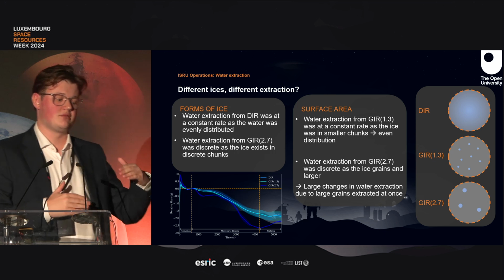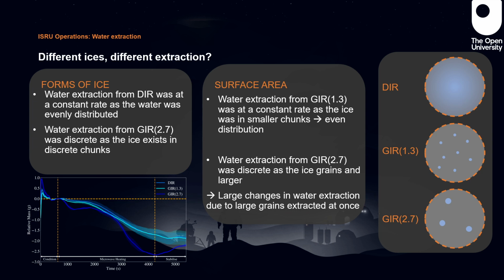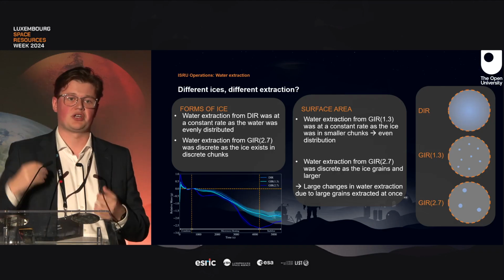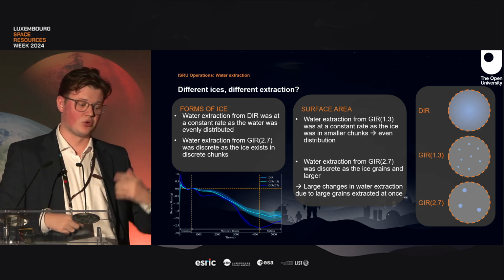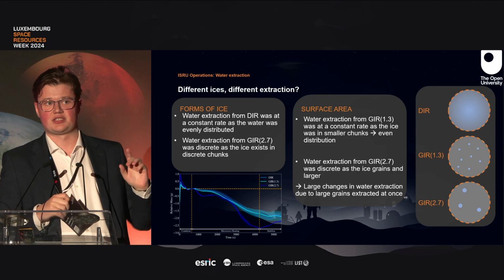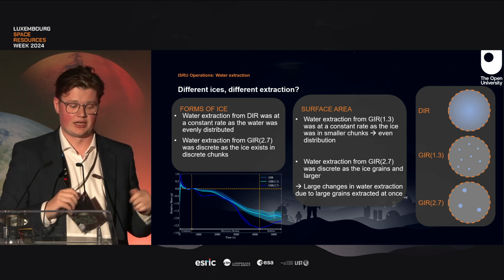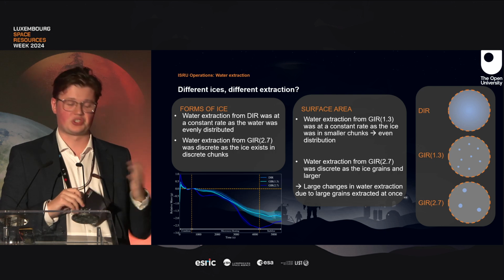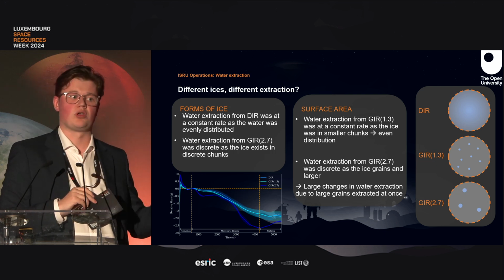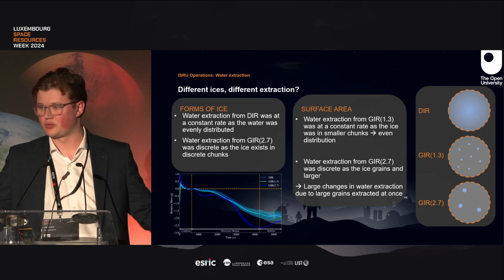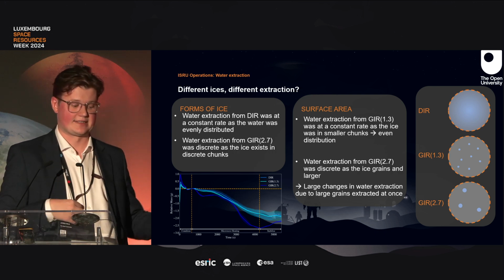From there, you have to then wait a while before the temperature in the core of the sample increases. However, the big drop in mass occurs because the individual grains are larger. So once they get to a high enough temperature, the vapor pressure in those grains is quite high, and it pushes forward with a higher pressure, and therefore your water mobility is increased. It's also why you're probably seeing that the granular ice with a 1.3 millimeter grain is lower in terms of the extraction. The smaller chunks of the 1.3 millimeter grains act more like a diffuse ice because it's more homogeneous across a sample. And so that's why those two lines seem to be fairly similar.